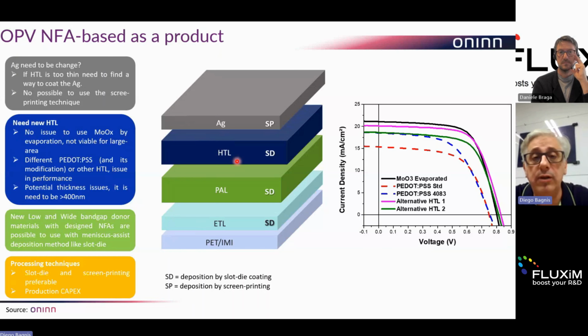As well for the PEDOT, if you are using just a really thin HTL, you are not able to use this technique. And so you reduce the performance, but you lose a lot of samples as well. So one of the challenges was exactly to improve the HTL and to achieve over 300, 400 nanometers in order to continue to use screen printing.